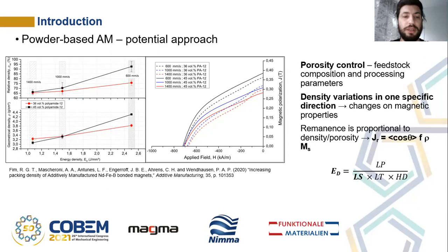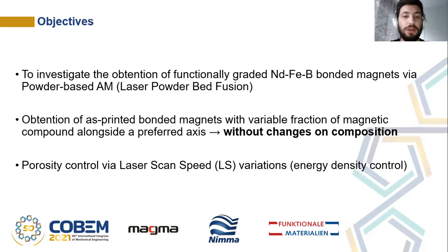Since magnetic properties are proportional to the porosity degree of the magnet, this emerges as a potential candidate to obtain functionally graded bonded magnets. Inspired by this context, this work aims to investigate the obtention of functionally graded neodymium-iron-boron bonded magnets, obtained via powder-based additive manufacturing. The main objective is to obtain magnetic samples with variable porosity in a specific direction via laser scan speed variations, without changing the feedstock composition.